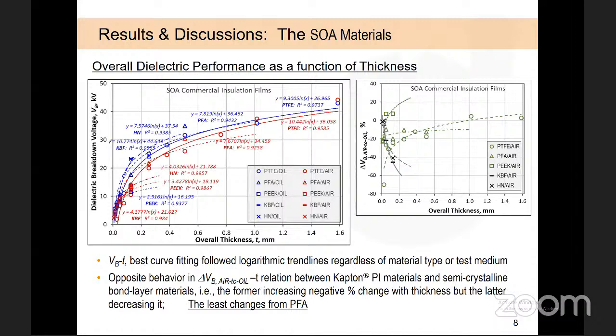Figures here summarize the overall dielectric performance of the representative SOA materials as a function of sample thickness, either in oil or air, as a baseline for this study. In most cases, they follow the logarithmic trend lines. Even though the VB values varied with the material types, the most interesting finding was the opposite behavior in the delta VB to thickness relation between Kapton and other semicrystalline materials, as changing the test medium from oil to air. The former goes down while the latter goes up with increasing thickness. In any case, PFA, which was selected as the best bond layer so far, showed the least changes.